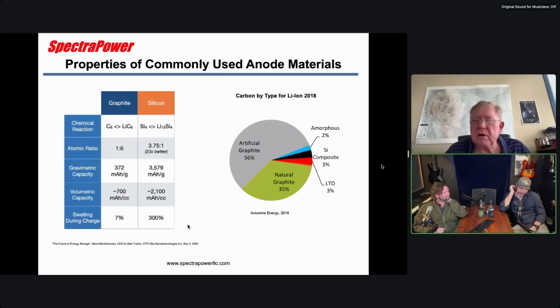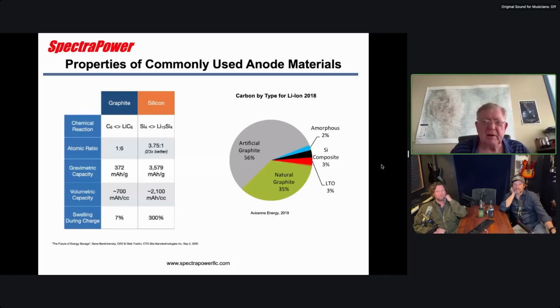Are they looking for ways to build the battery so that it can just accept the swelling? Like, in other words, the case of the battery itself can hold the different sizes? Yeah, the problem with that is then it gives up a lot of the advantage of the silicon, because you have to have a bigger case, which is heavier, that kind of thing. So what they typically try to do is take care of it on the micro nano scale. Okay. Where they allow for a certain amount of swelling in the material. Sometimes they'll encase it or put it in with graphite because it allows some room for swelling, so you don't really see it. But yeah, you see pretty sophisticated methods to try and solve that.